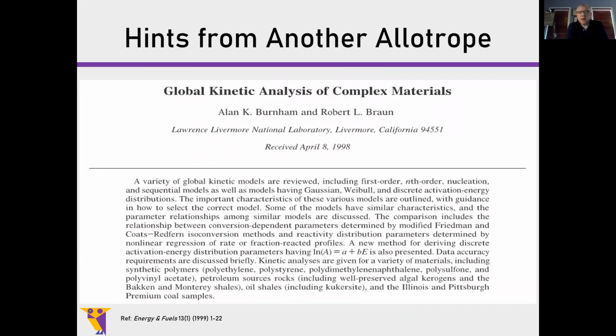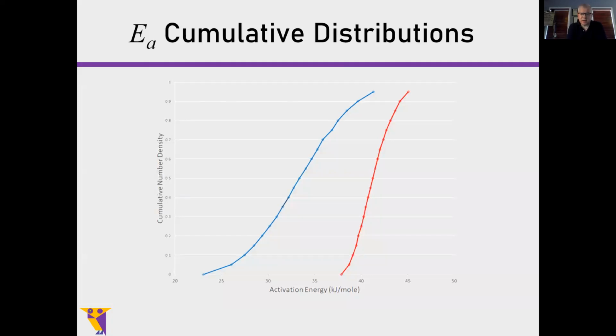Well, like I say, hints from another allotrope. Studying coal has been a long use of TGA. And they've developed something called the distributed activation energy model, which says that if I have a surface like graphite or coal or any of these other carbon materials, the surface doesn't actually have a single activation energy, but actually has a distribution of them. And if you use the equations for that and you take that same data that I showed you for the 7-6, you get an idea of how different these activation energy distributions look for each one of the components. One is reasonably narrow. The other is kind of broad.